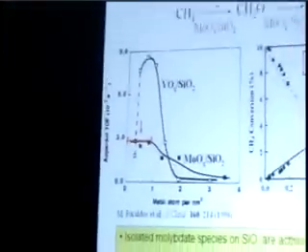So in the literature, it's been shown both for vanadium silica and, for our case, molybdenum silica, that if you stay in this regime, here shown in red, where you have isolated molybdate units, so having 1 molybdenum per center, that the catalyst has essentially uniform activity.